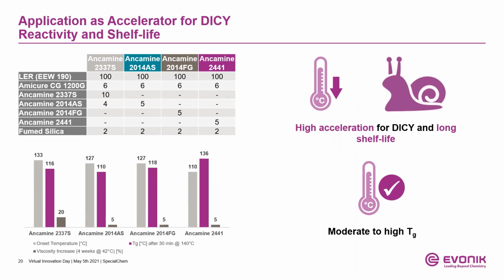Let us now turn to the potential of the modified aliphatic amines when applied as an accelerator for dicyandiamide. Here it must be noted that Ancamine 2337S cannot accelerate dicyandiamide by itself, but it can further boost Ancamine 2014 or 2441 accelerated systems. This topic will be addressed in more detail when we are going to talk about fast green strength build-up later. Regarding onset temperatures and the thermal stability after the standard curing schedule, in this case, it's 30 minutes at 140 centigrade.